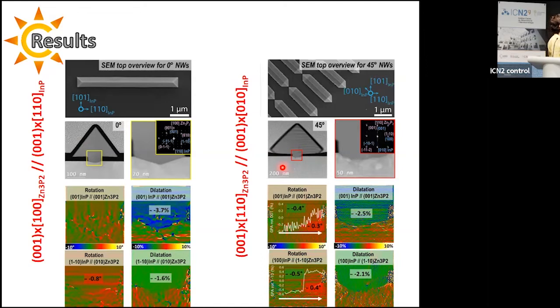In order to investigate possible plane dilatation and rotation within the nanowire after growing with this methodology, we perform a geometrical phase analysis by considering rotation and dilatation of the atomic planes that are parallel to the substrate surface and perpendicular to it, finding that in all the cases, the plane rotation is minimal, while regarding the plane dilatation, we can observe that in all the cases, the zinc phosphide planes, which are depicted here, are compressed with respect to the indium phosphide, indicating that the material is able to adapt.